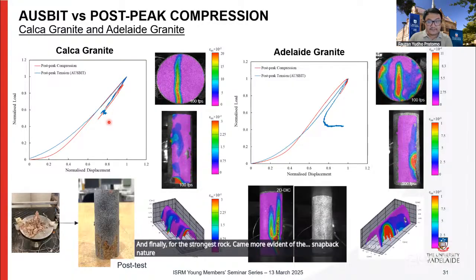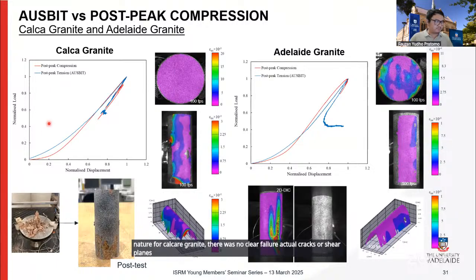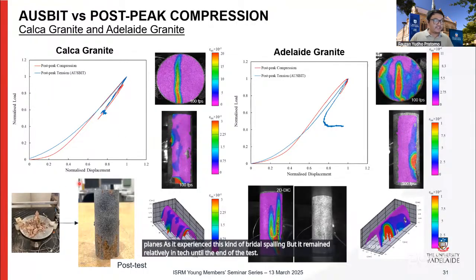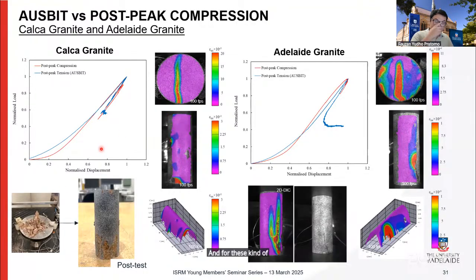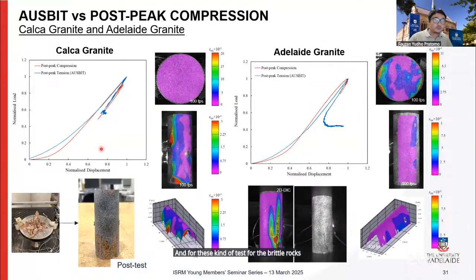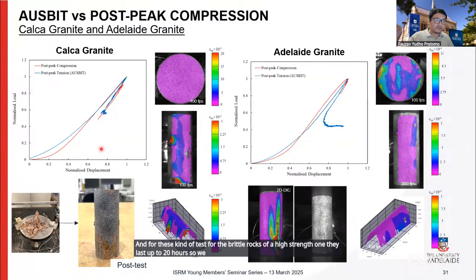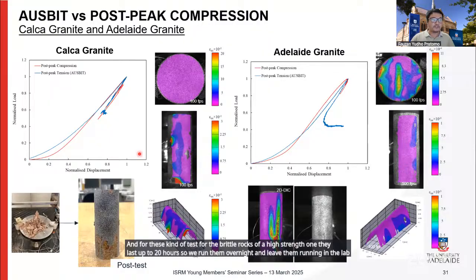For the Calca Granite, there were no clear failure axial cracks or shear planes, as it experienced a kind of brittle spalling, but it remained relatively intact until the end of the test. And for these kinds of tests, for the brittle, high strength rocks, they last up to 20 hours. So we run them overnight, leave them running in the lab, and get the results the next morning.